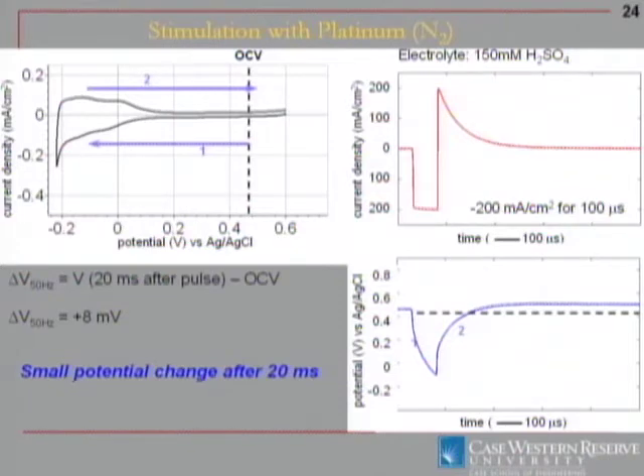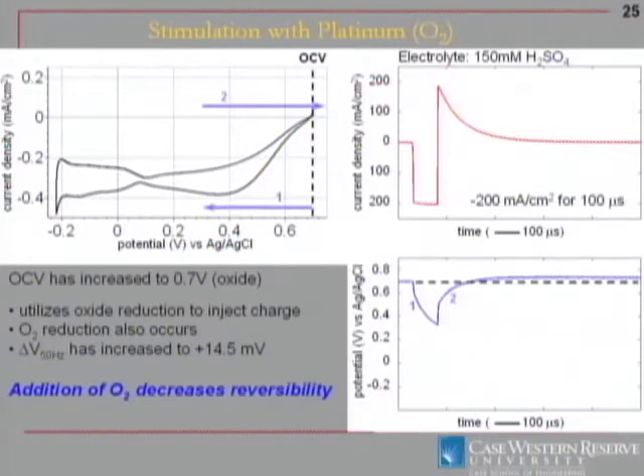And when we introduce this pulse, we do see the potential go higher, not by too much. This is a nitrogen purged electrolyte. It only goes up on the order of 10 millivolts after a single pulse. But that's nitrogen environment. You add oxygen to the system, the Voltammogram will look different. Again, we're sweeping it with a current pulse. The potential ends up in this region here, goes back. It goes beyond, again, the open circuit voltage where we started. The voltage increase is more with oxygen present.